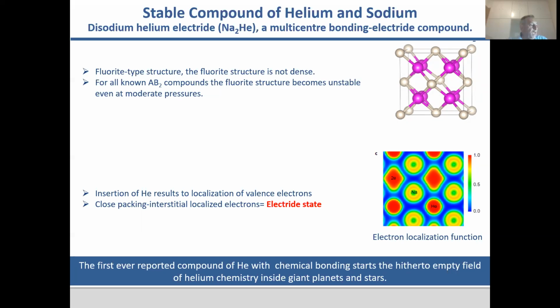It's known that sodium, this is one of the first slides I saw, forms an electride at very high pressure, at about 200 GPa. So part of the story is that helium forced the system towards an electride state. Nevertheless, this was the first stable compound between helium and another element, which we believe started this field of helium compounds. And again, helium is very abundant in the universe, so we may think again about how helium exists inside planets under high pressure.